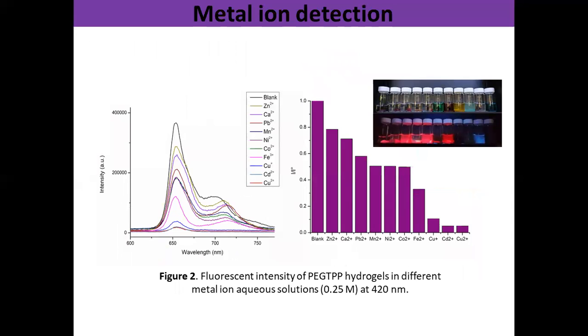Ten metal ions were chosen to study the metal ion selectivity of the PEG-TPP hydrogel. Figure 2 illustrates the fluorescence intensity of the PEG-TPP hydrogel after immersion in different metal ion aqueous solutions containing copper 2+, copper +, iron 3+, zinc 2+, lead 2+, cobalt 2+, calcium 2+, nickel 2+, cadmium 2+, and manganese 2+, and a solution without metal ions, a blank, at 420 nanometers excitation. We can observe a decrease in the emission intensity of the hydrogel after immersion in the metal ion aqueous solutions, but it is worth noting the response of copper 2+ and cadmium 2+ ions, which almost completely quench the emission.